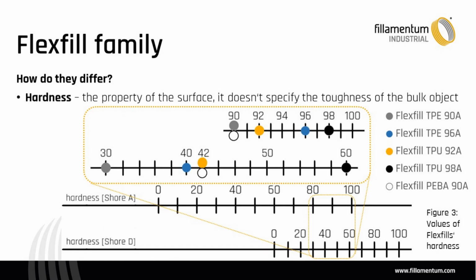And also TPE in high hardness has the second lowest value of the hardness. Then we can see, for example, that TPU 98A has 60 Shore D, which is a higher value than it should be, by approximate comparison. So we need to compare the materials in the correct way, the same measurement of the specimens, the same Shore hardness.